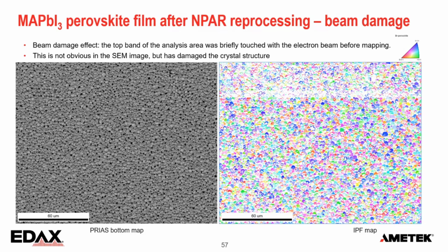So when you are imaging and you are taking a little bit too long to focus and do the astigmatism corrections, then you have effectively destroyed your crystal structure. So this is a very nice illustration of what happens. Here we just measured a little bit longer and everything is gone.